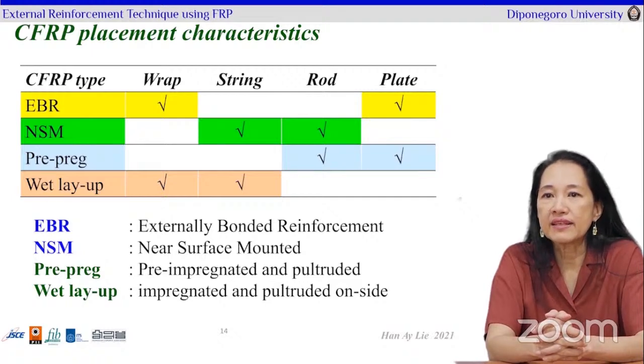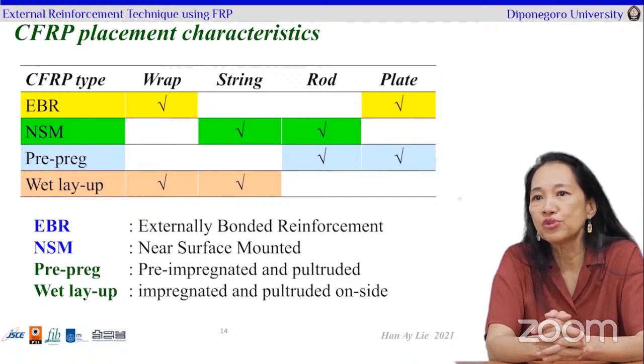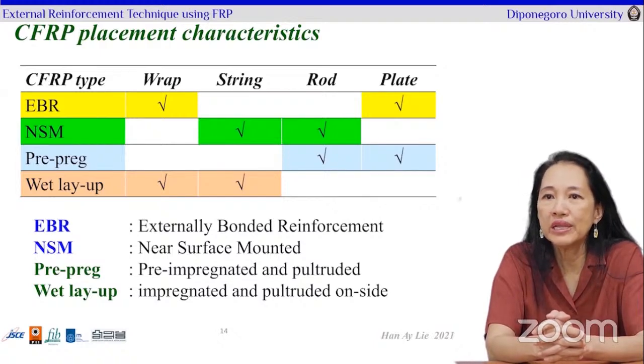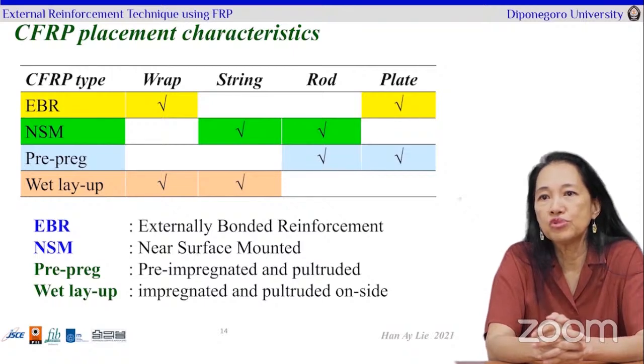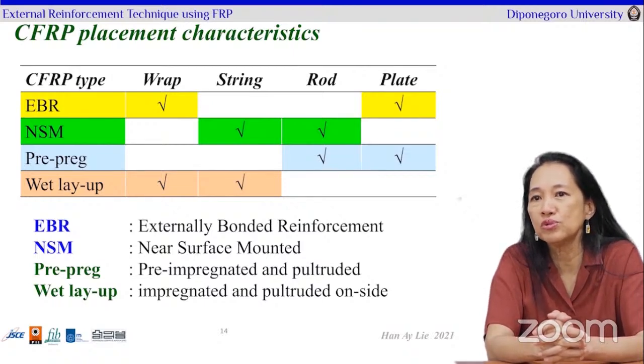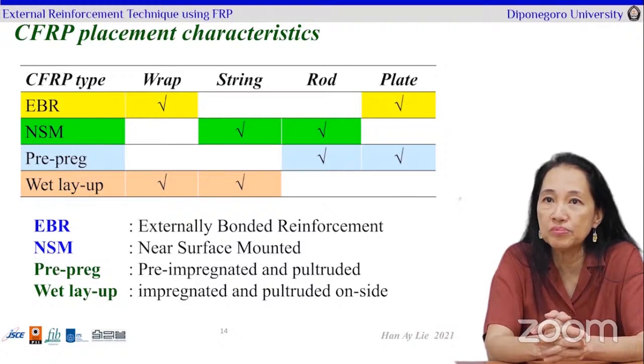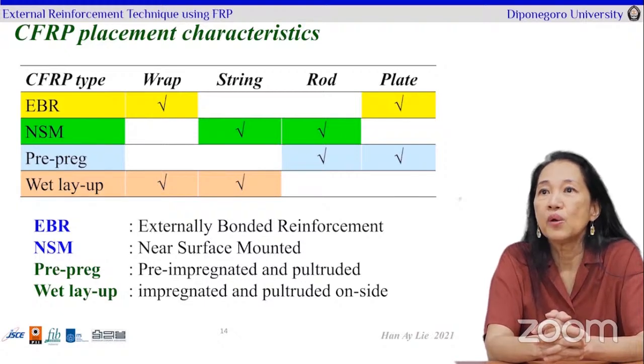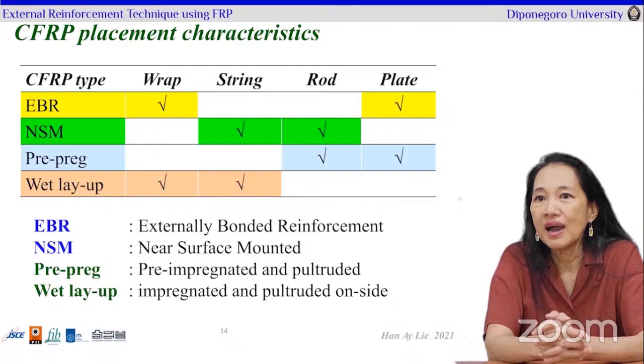We have NSM, which is near surface mounted. Here we will have to cut a hole in the concrete to put in the FRP and close the hole with the epoxy. So these are two entirely different systems. We can see the wrap and the plate are externally bonded outside, but the string and the rod are implanted or embedded into the concrete.